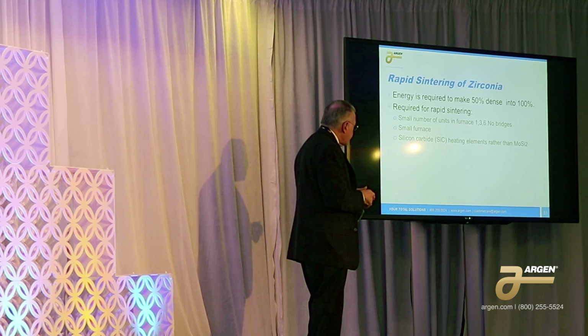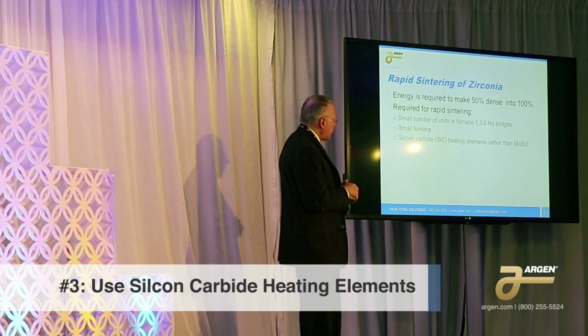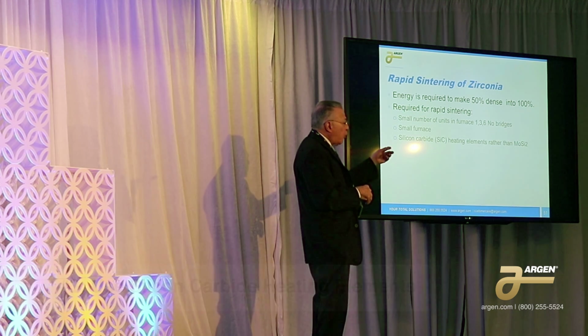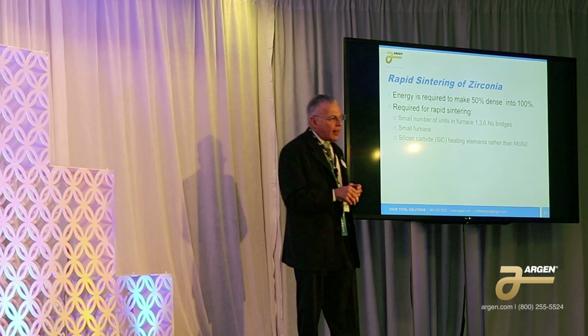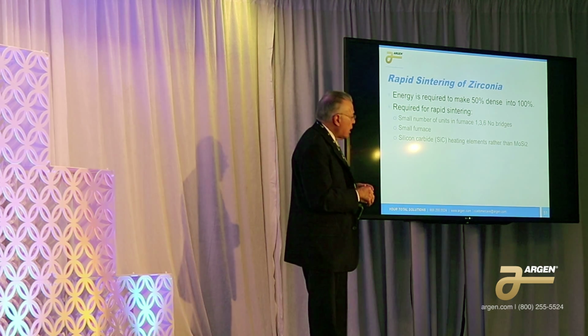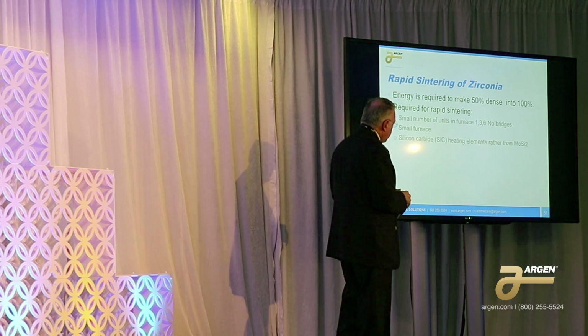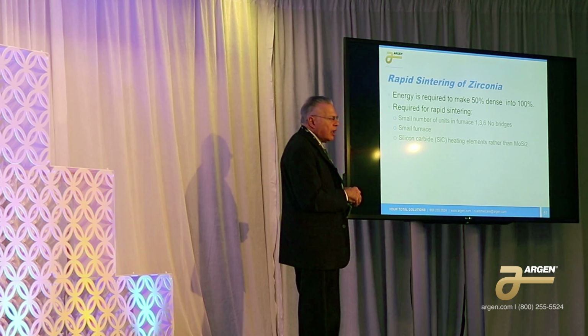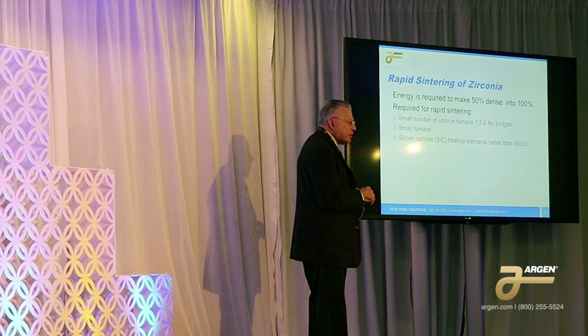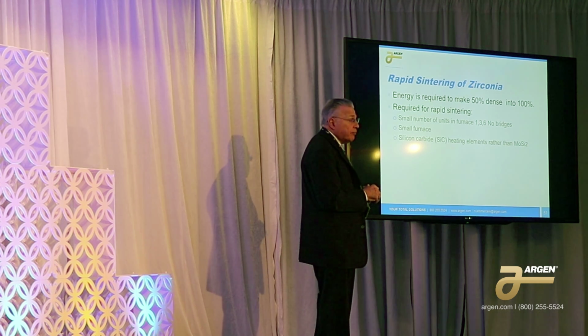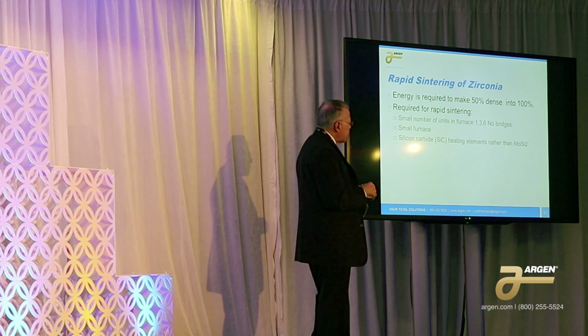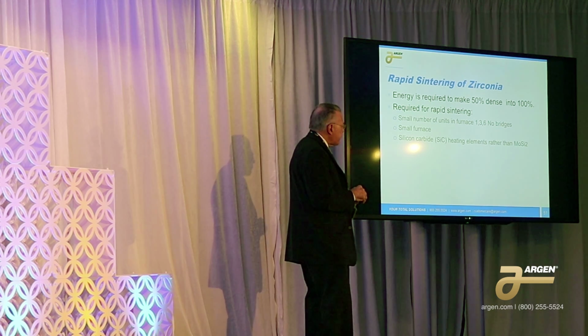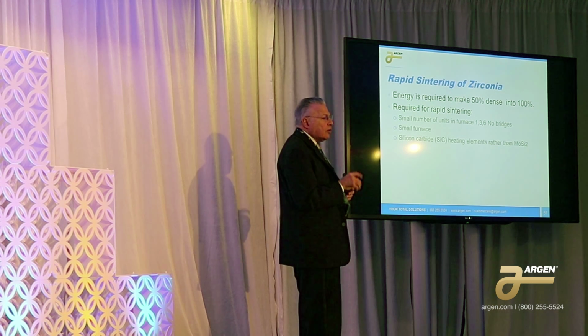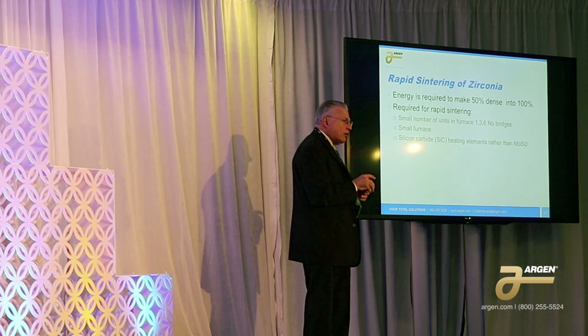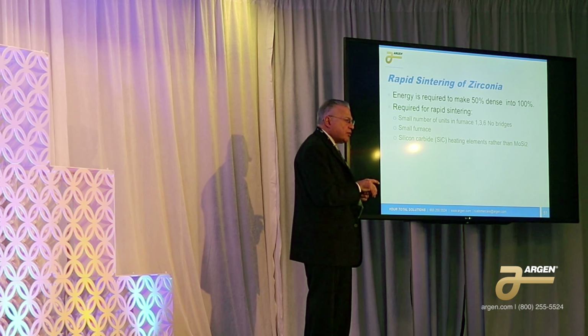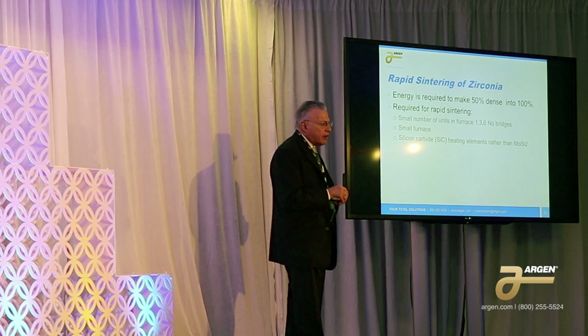And basically, you need silicon carbide heating elements rather than molybdenum disilicide. If you cool the molybdenum disilicide furnaces down too fast, the heating element may crack. The silicon carbide furnaces don't, however. Those are very good. You may have seen ads for the Austromat furnace from Dekema, and those are very good. And there are two types. One can hold like 20 units, and the other can hold like 40. But in the fast cycle, they're recommending no more than 1 or 3 single units, no bridges, 1 or 3 units in the one unit, and no more than 6 or 7 in the other.